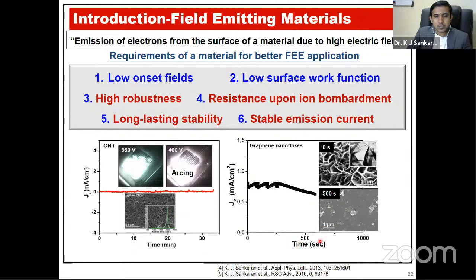So it cannot last, it cannot stay stable even for nearly 250 seconds. After that, the current starts to decay. So we need a stable emission current with long-lasting stability and also high robustness with resistance to ion bombardment, that is, in a plasma environment, if you are looking for microplasma applications.